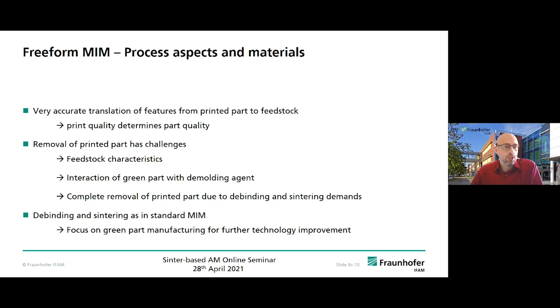I don't want to hide some challenges. The main ones we see are in the removal of the printed part. Your feedstock has to have some characteristics, some strength, so that it withstands some swelling of this printed part that may occur. You have to prevent some interaction with this demolding agent. And especially for the metal parts, you have to make sure that you remove this printed material completely, as it's an acrylic material and those are not nice to burn out and may leave residual material that disturbs the sintering of your material or adds carbon, for example, and changes the material.